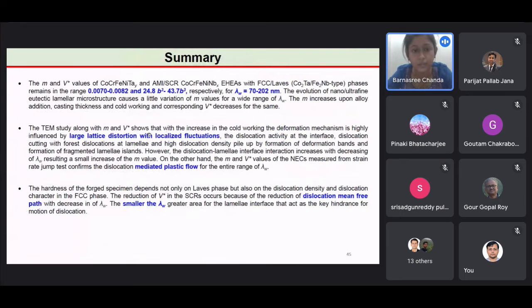Therefore, from this we can conclude that the strain rate sensitivity remains in the range of 0.0070 to 0.0082 and the activation volume in the range of 24.8 b cube to 43.7 b cube. In this range, it shows that the deformation mechanism is dislocation mediated. Also, the TEM study along with the strain rate sensitivity and activation volume shows that with the increase of the cold working, the deformation mechanism is highly influenced by the large lattice distortion with localized fluctuation.